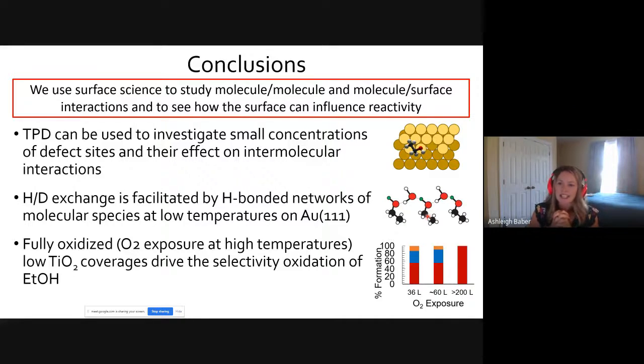One thing that I've been really excited about is being able to see these small concentrations of defect sites on the gold surface. We've done some work on silver as well. I didn't have time to talk about that today. Another interesting thing that we were very surprised by was this hydrogen-deuterium exchange between molecular species on an inert gold surface. And then finally, being able to drive that selectivity and look at the coverage of titania and the exposure of oxygen, we found that we're able to selectively oxidize ethanol to acetaldehyde.